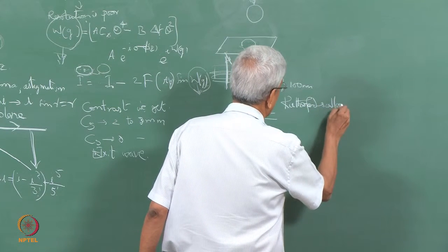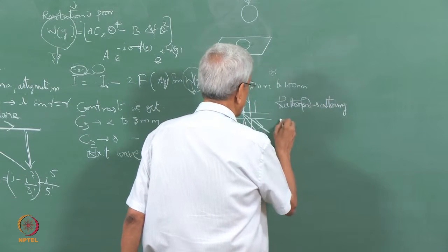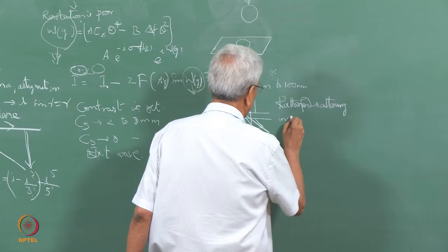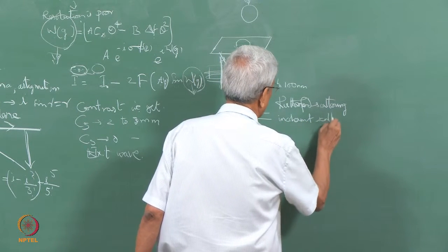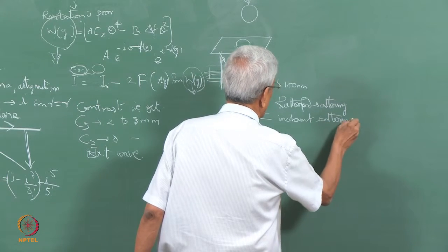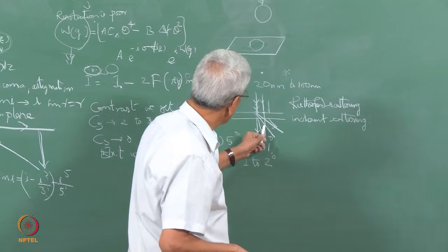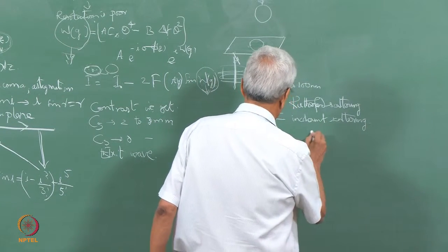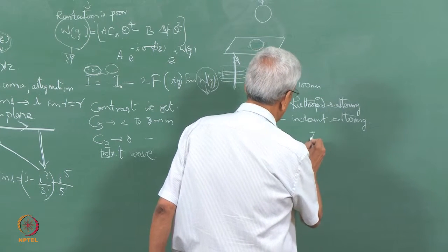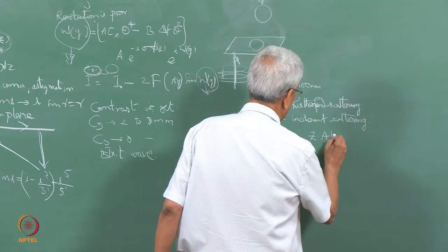It is an elastic scattering, but what essentially happens in this scattering is that it is an incoherent scattering. And more than that, the intensity of the beam in a specific direction depends upon Z, that is, the atomic number of the element.